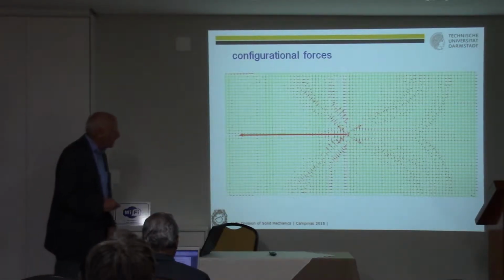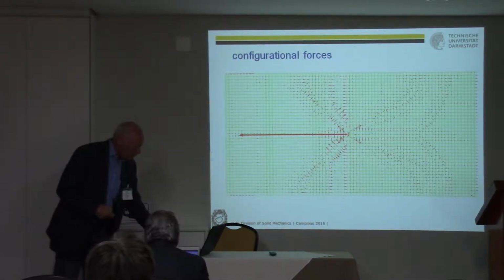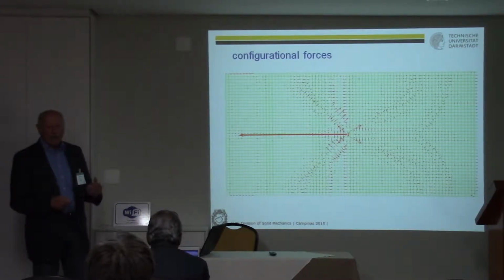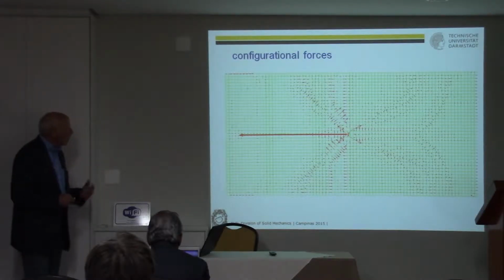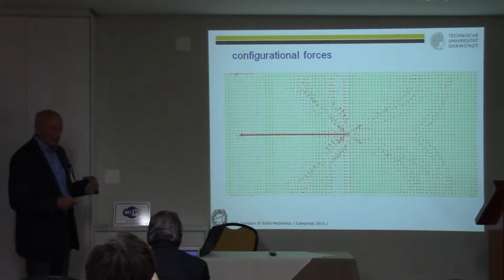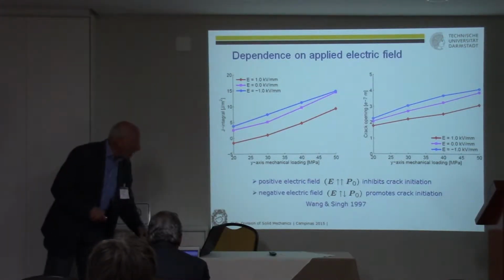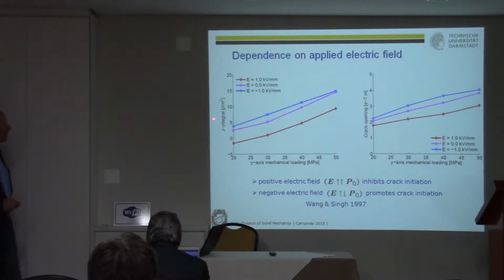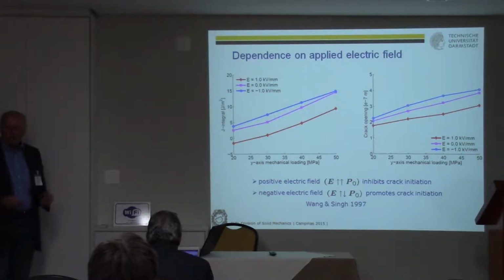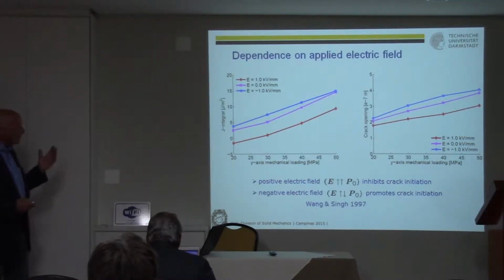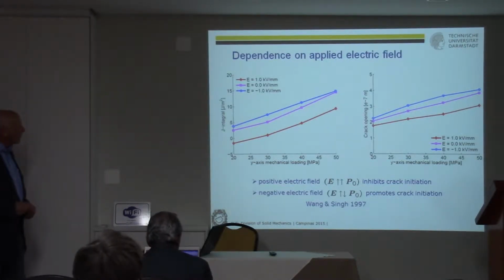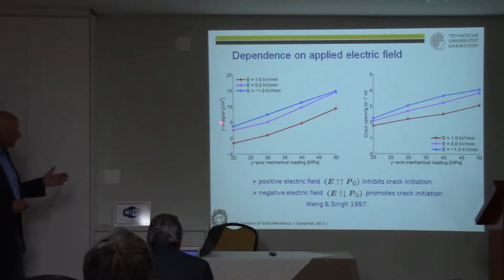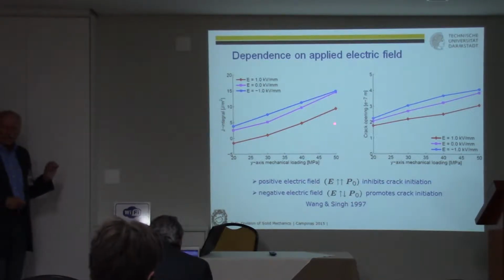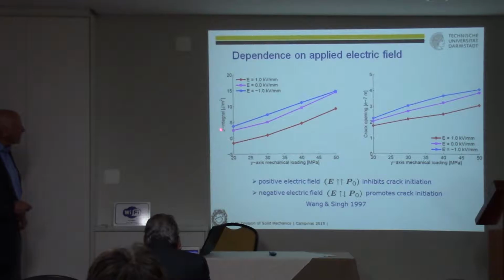And usually people take this to compare it with the experimentally determined force which is necessary to really drive the crack. And here are some results. Plotted is the J integral. The J integral is a usual quantity used in fracture mechanics; it describes the driving force on a crack tip. And in this case, this is nothing else than a configurational force. J integral and configurational force at the crack tip are exactly the same.